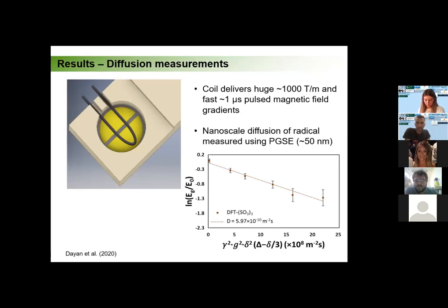It's this pulse program called the pulsed gradient spin echo. I'm not gonna get into it, but basically this is the measurement. We apply some gradient, we measure our signal, and then we apply a bigger and bigger gradient, and from this we can extract the diffusion coefficient.